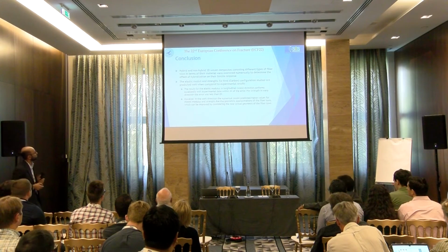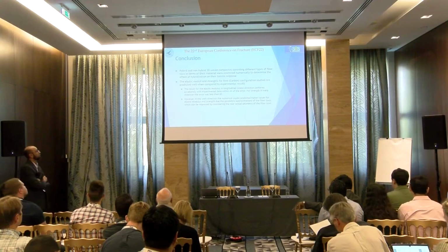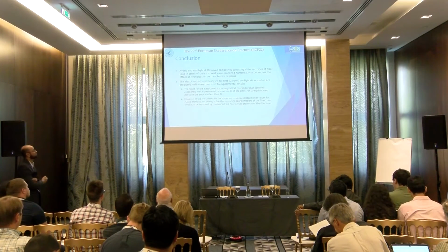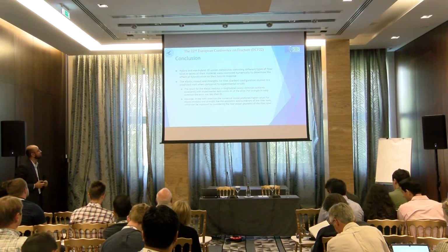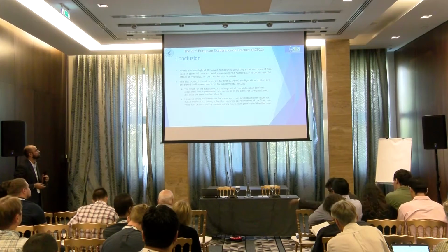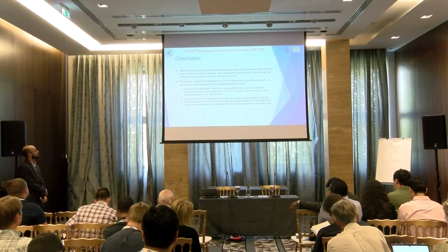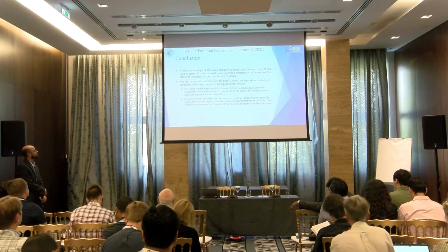Now I will conclude. The result for the elastic modulus in the longitudinal warp direction conforms excellently with the experiments within 4% of error. For the strength in the warp direction, the error was less than 8%.